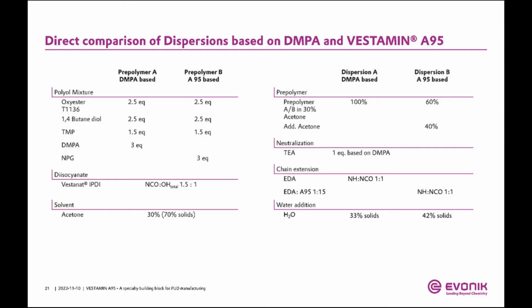Because as we all know from the evaporation, if you do a batch evaporation, the last couple of percent take 80% of the time, right? So the first big portions, that goes off easy. And then really reducing the last 1, 2, 3% of your acetone, that will take the longest time. So it really doesn't matter so much where you start from time-wise. Energy-wise, you're right. Energy-wise, this needs to be taken into account, that you have to evaporate more acetone.